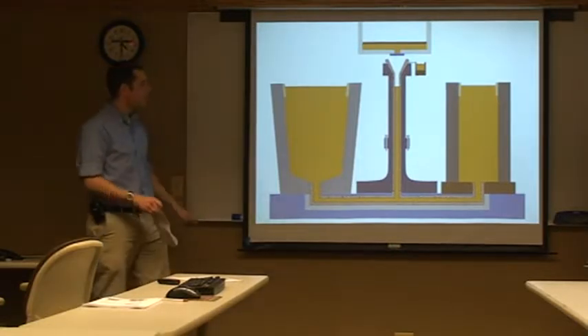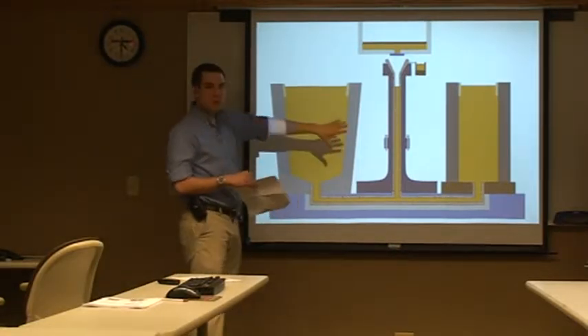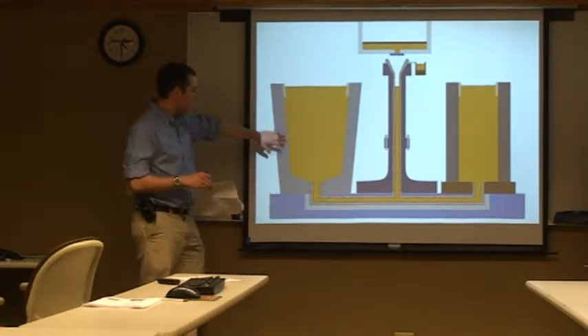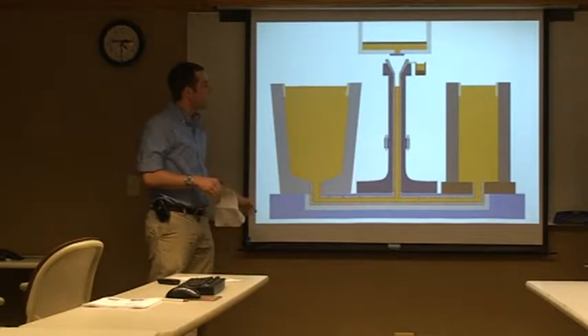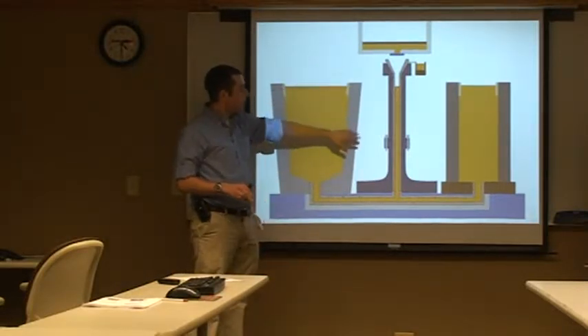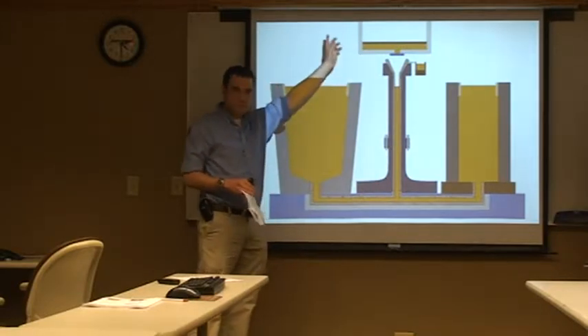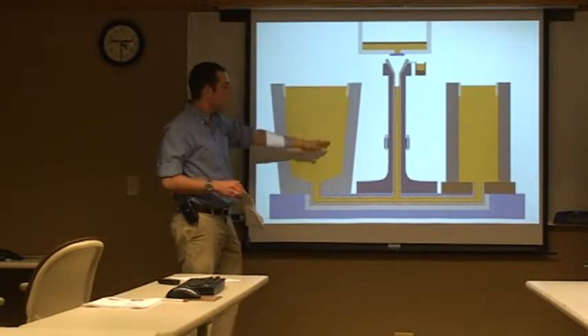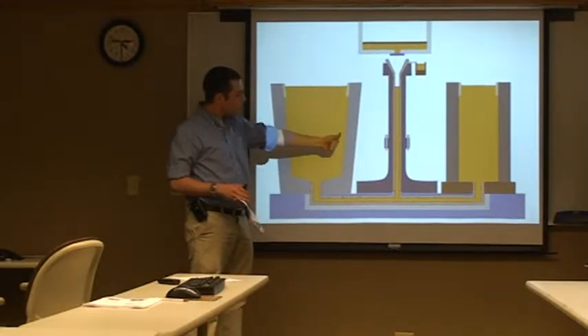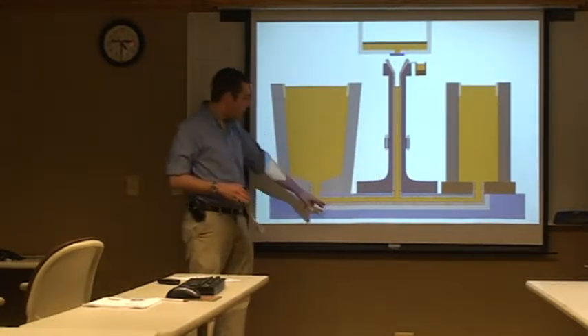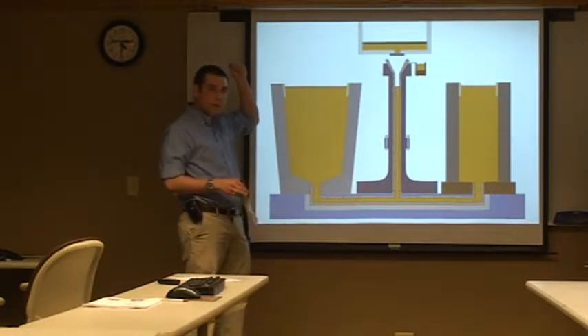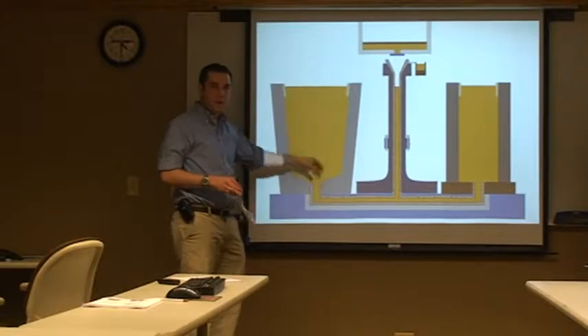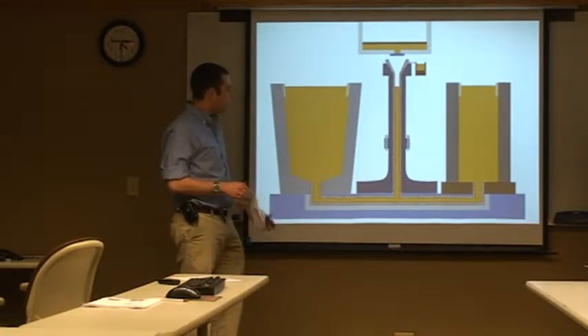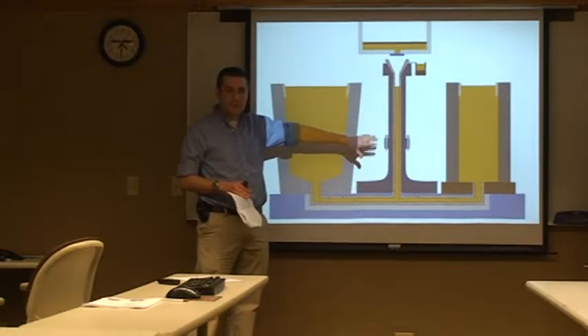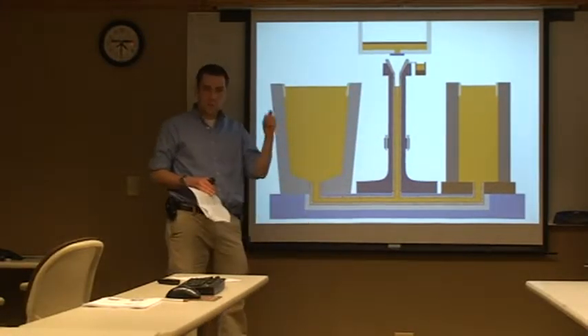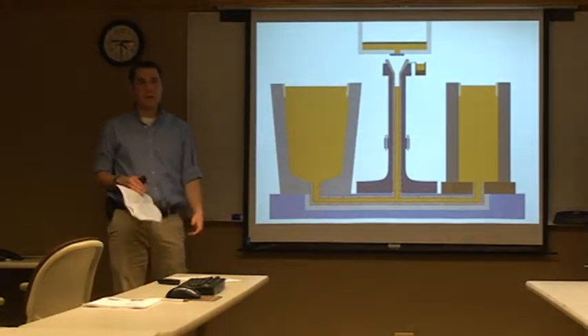Okay, what we'll do is we take the molds off first. If it's a mold like this, we'll have to dump it out. We can't just strip it up straight. And then we take the trumpet off, and there'll be this vertical cylinder of steel there. And normally when they rip that out, the runner bars will come out too, and it breaks off right here when they take the ingot away, because this is a very small diameter compared to the rest of the steel. So we'll be left with these kind of skeletal remains of the trumpet and the runner system, which we cut up and use as scrap in another heat.